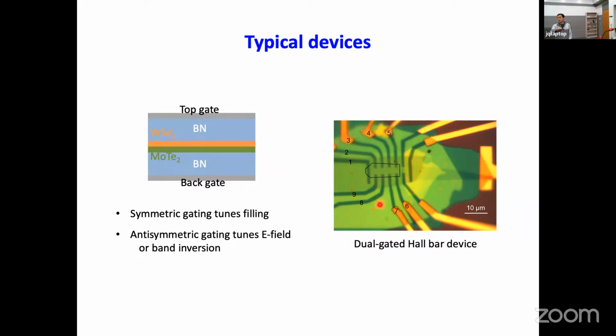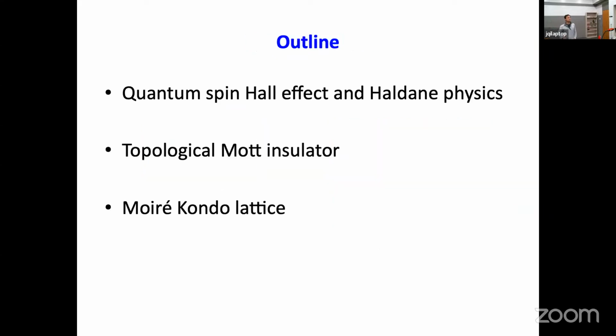And we can just pass a current and measure resistance and Hall resistance in the material, which I'll focus on. You can also shoot a laser in the middle of the device to do some optical spectroscopy. But anyway, this is the general setting of this kind of device structure. The important thing here, which I'll come back to over and over again, is that there are 2 gates. We can independently tune the electric field and the filling factor, or the doping density, in the material.